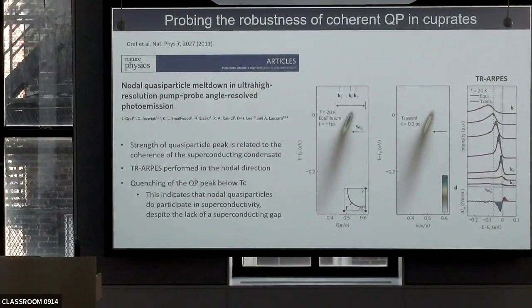And then the experiment is we go with our pump. We somehow harm the superconducting coherence. I don't think this was quite the interpretation there. So this has been to me a very puzzling aspect. What goes on with the pump is that the coherence of the nodal quasi-particle goes down, the amplitude goes down. And let me just say that this was limited to the nodal direction because with the kind of photon energy available in that system, that's all you can see.